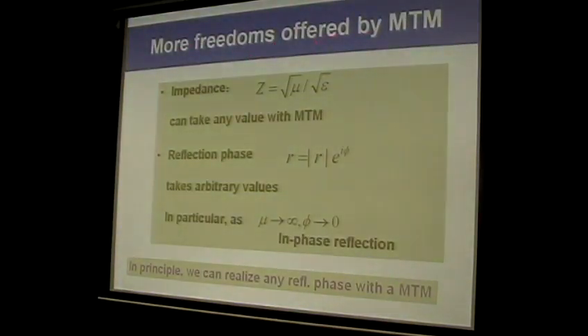Now, more freedom is offered by metamaterial because the impedance is fixed by not only epsilon but also mu. Because metamaterial can have arbitrary values of epsilon and mu, it means that the impedance can take arbitrary values upon careful design. That means the reflection phase, if we define the reflection phase like this, can take arbitrary values. In particular, if you define a system with mu tending to infinity, you find that the reflection is actually in phase.